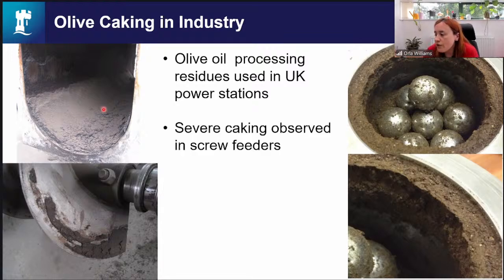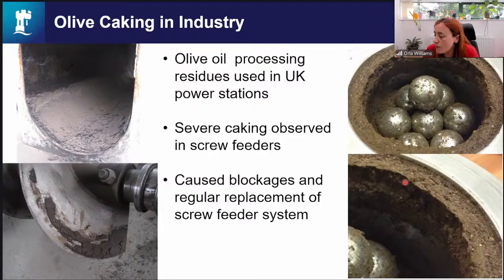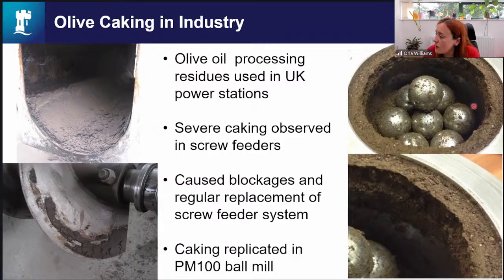So they observed this severe caking within the screw feeds and asked us if we could replicate it in the lab, or look into it a bit more. So we took some of the olive cake and put it into a PM100. And as you can see here from the ball mill, we replicated the sticky cake on the side. You can see it was actually a very solid cake, and you had to chip it off with quite some force. And it was stuck to all the balls as well.